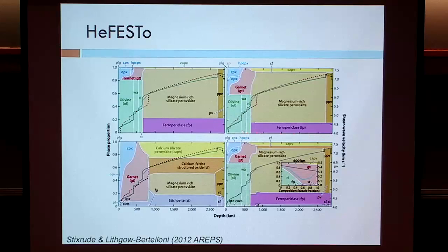In this case, I've plotted it along a self-consistently computed mantle isentrope. And so for pyrolite, which is this phase equilibrium here, we get the dashed green curve. And you can see olivine, wadsleyite, ringwoodite, those polymorphs. You can see the pyroxenes dissolving into garnet. You can see calcium perovskite exsolving out of the garnet there. Lower mantle dominated by perovskite and ferropericlase, and there's the post-perovskite transition there.